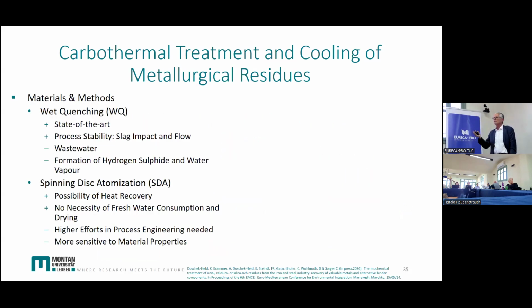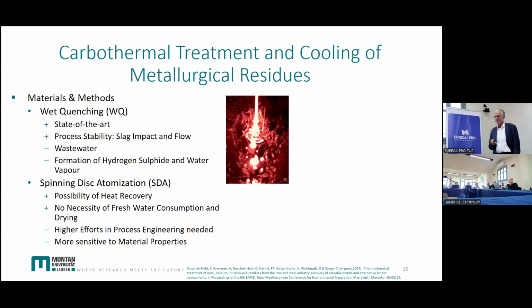So how do we cool the slag? Traditionally, we use wet quenching. That's very simple. It's state of the art. You just quench it with water. The process is quite stable. What is the disadvantage? You produce wastewater on the one hand. You have formation of hydrogen sulfide and water vapor, and this water vapor cannot be used for energy recovery.